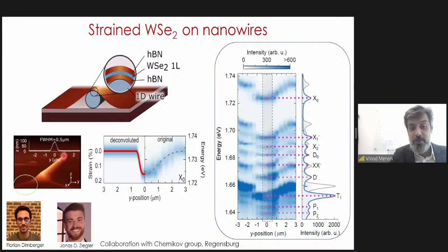This is an atomic force microscope image which shows how the 2D material wraps around. What strain does is it effectively creates a potential minimum for the carriers inside the system. And you can see that clearly here. This is a map where I'm going from one end of this structure over the wire and down here. And you will see that as I go over the wire, all the energies of the excitons get redshifted. Redshift meaning that I've got a lower potential minimum there. And then I go back and everything returns. This step is only caused because I'm only going one way. It has nothing to do with the physics. If I sweep the other way, I would have seen a step on this side. So you will see that all the excitonic species in the system are redshifted. But again, the main message is that strain introduces a potential minimum.